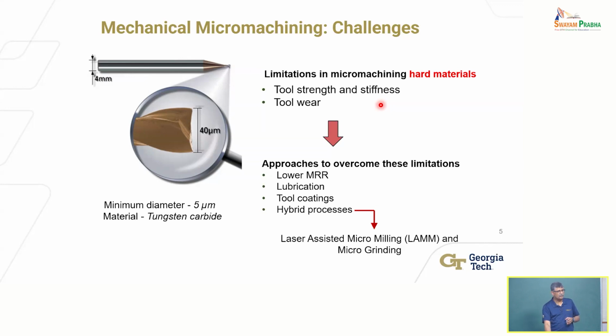Obviously, that's one reason why the tip is conical. You see the diameter of the shank is 4 millimeters. It's not that small, but the tip, which has a small length and has a diameter of 40 microns, is a very small portion of the overall tool. It's to minimize compliance or lack of stiffness. They've already done that, but still, depending on what you're cutting and what forces are involved, the rest of your machine structure, if it's not rigid enough, can cause problems in terms of deflections, for example. So those are a couple of things.